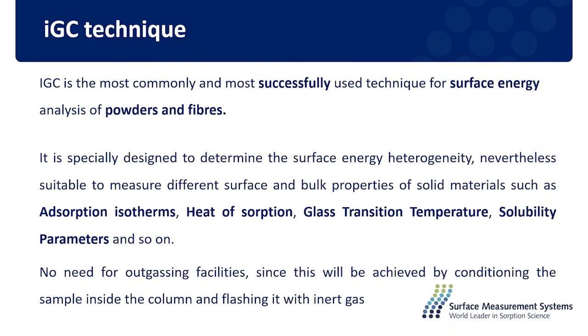But inverse gas chromatography is a really powerful technique, and it's the most commonly and successfully used technique for surface energy analysis of powders and fibers. It's specially designed to determine the surface energy, nevertheless suitable to measure other different surface and bulk properties of solid materials. For example, adsorption isotherms, heat of adsorption, glass transition temperatures, solubility parameters, and so on. And in the case of IGC, the good thing is that you don't need an outgassing facility, because conditioning and outgassing can be done inside the column, and it's part of the experiment.